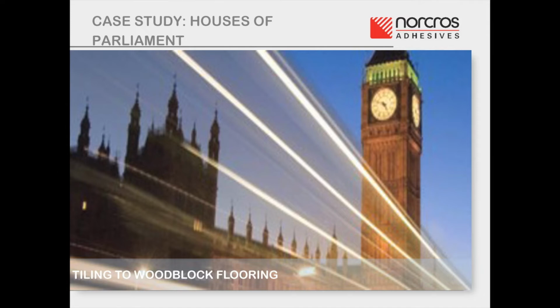A slurry bonding coat consisting of 2 parts adhesive mixed with 1 part SBR primer was brush applied onto the tiles to provide a key before installation. By using a 2-part rapid setting elastomeric adhesive suitable for tiling to wood surfaces, it was possible to fix tiles securely over the woodblock flooring after the floor had been prepared. An epoxy grout was then used in all areas to ensure a hygienic, easy clean surface.